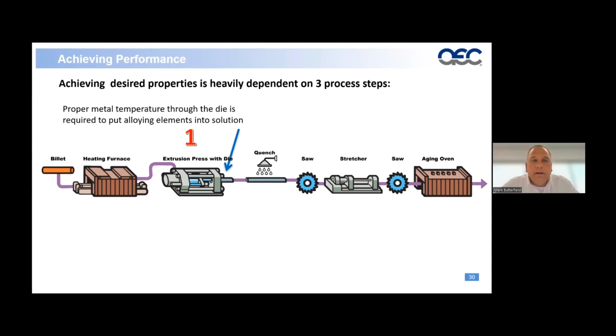But the proper metal temperature through the die is required to put alloying elements into solution. So the key thing we're looking for is, what is the input temperature of that billet? How much temperature are we going to develop or rise in temperature through the deformation process? And are we going to yield an exit temperature that's appropriate for that alloy and the quench process that's required?